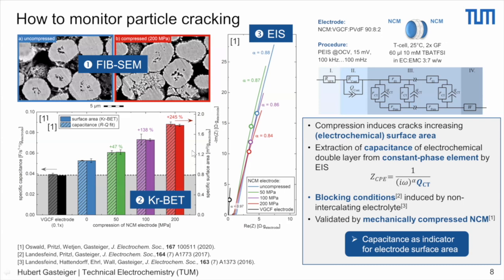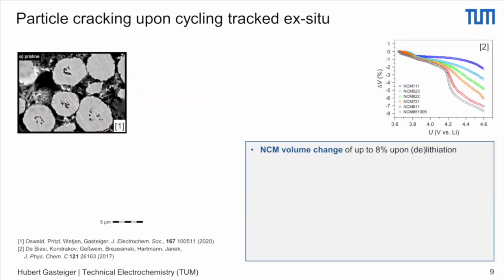And what we can show is that there is actually a very good agreement between the capacitance increase and the increase in the BET surface area. So we can use the capacitance of the cathode electrode as a measure of the effective BET area increase, right? Of course, we have to do the same subtraction of the capacitance contributed by the carbon. So then we use this method to try to follow the particle cracking upon cycling.